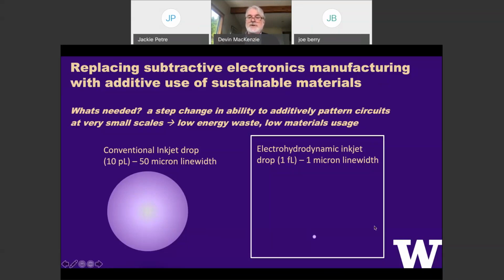We can actually produce submicron features from the drops. We can pull drops out of the head that are a femtoliter, so 1,000 to 10,000 times smaller than conventional. And so we can print these extremely fine line widths. That's really interesting for printed electronics broadly, to get into high performance transistors, sensors, all that.